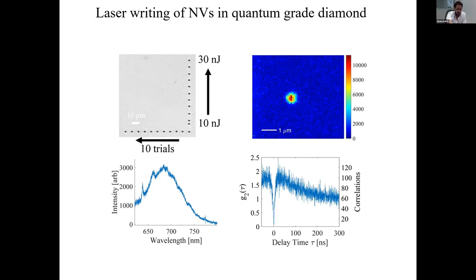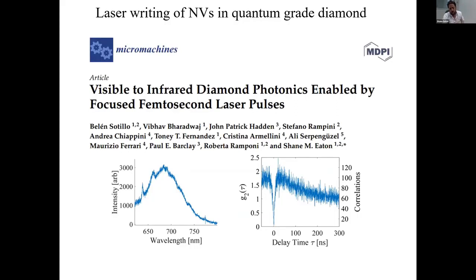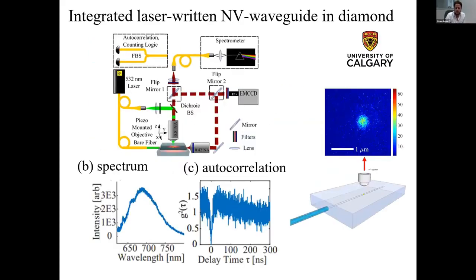Here on the bottom left, you can see the very typical photoluminescence spectrum from the NV center showing this nice peak at 637 nanometers. You see the confocal photoluminescence on the top right showing this nice emission. And also proving that we have a single photon source, we see the G2 going below 0.5. And so we're quite pleased that we could also fabricate in our labs this NV center on demand.